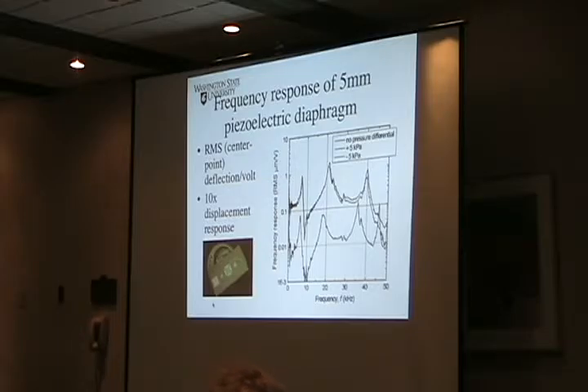Actually, I'll do a couple sets. This is air. We do it with the fluid behind it, and that'll just drop the Qs a lot and drop resonant frequencies because there's a large effective mass, and it acts as a squeeze film as the fluid evaporates and wicks down a wicking structure that brings the fluid from a reservoir into a thin, hot area.